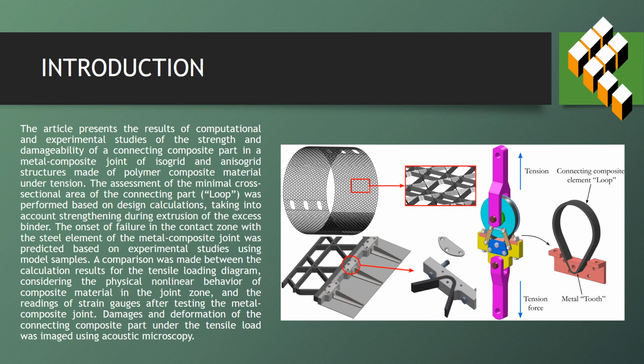The article presents the result of computational and experimental studies of the strength and damageability of connecting composite part in a metal composite joint of isogrid and anisogrid structures made of polymer composite material under tension. The assessment of the minimal cross-section area of the connecting parts was performed based on design calculations taking into account strengthening during extrusion of the excess binder.